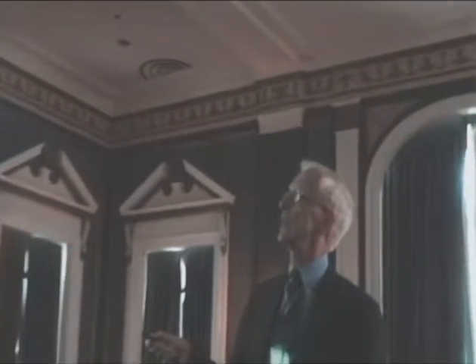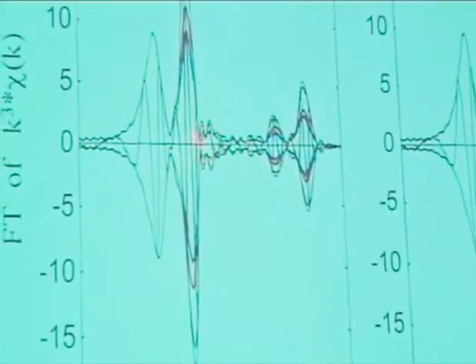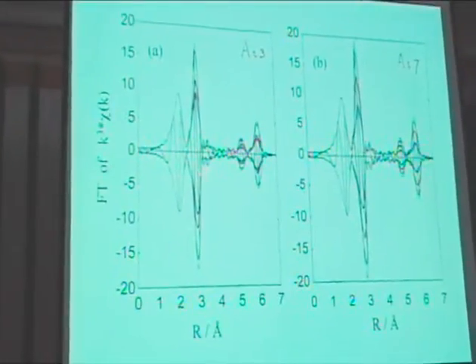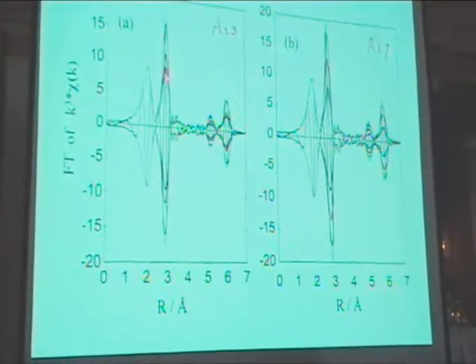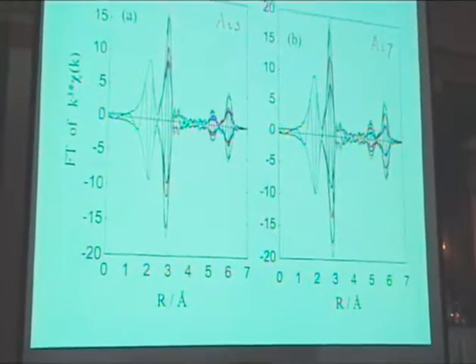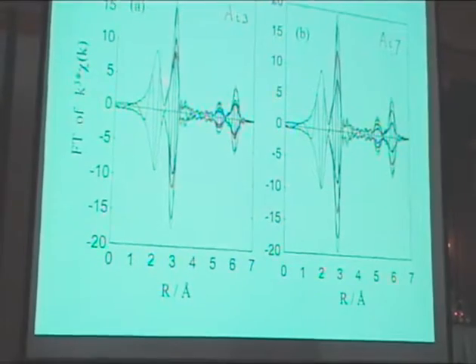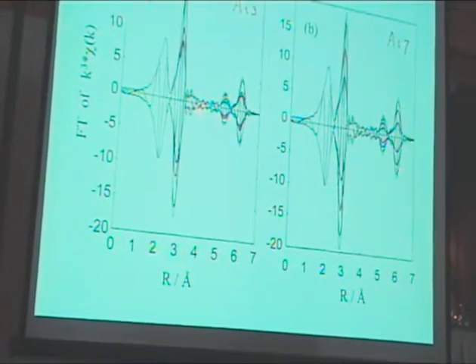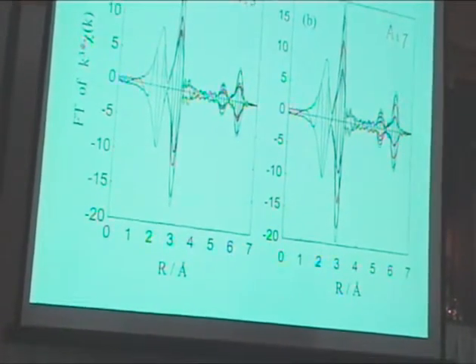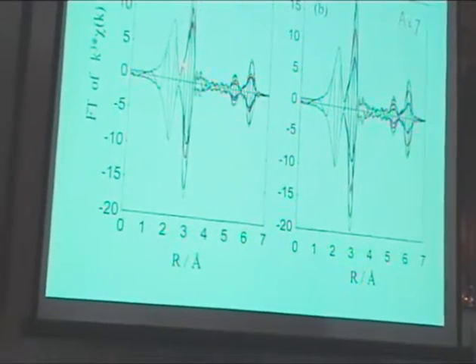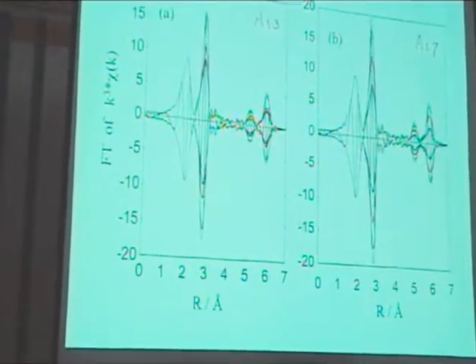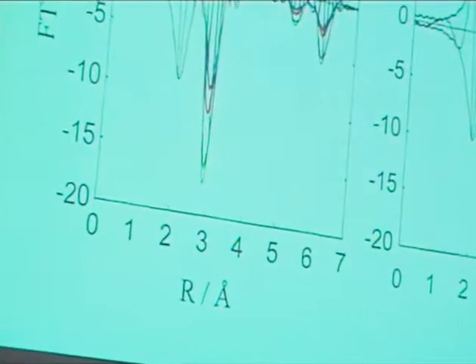What you see is that with model 1, just giving the molybdenum atom a random position, but no distortion at the edge yet, it is almost impossible to make this second peak lower than the first peak. I must go to outrageous randomization, Monte Carlo thing, to get it lower. And this is impossible, and I still have too much intensity here. So that model, that I just give every molybdenum atom freedom, doesn't work. I must go to models which have distortion at the edge.